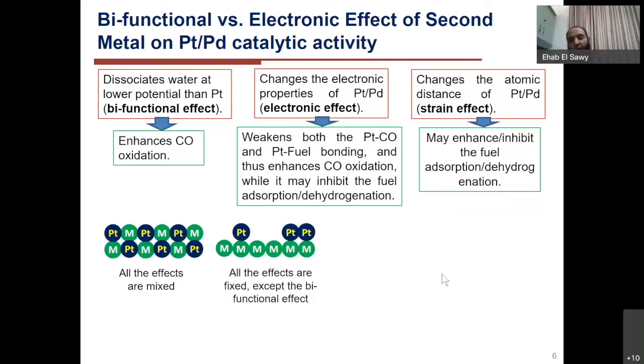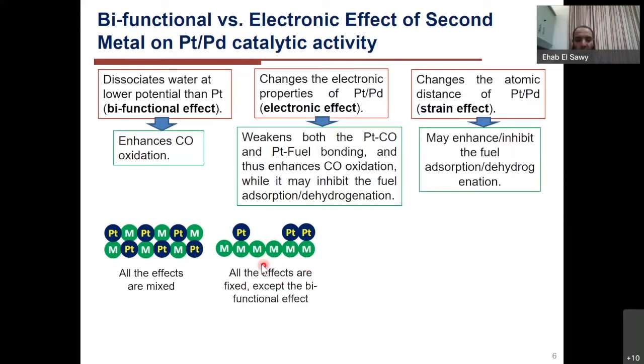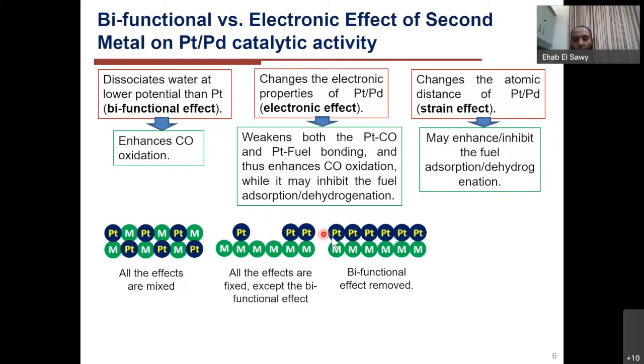So if we have the core in here and then we have a sub-monolayer of the shell on the top, in this case the electronic effect on these atoms and the strain effect are constant. However, if we are changing the shell coverage, we are only changing the bifunctional effect as the second metal is exposed. However, if we are totally covering the metal with one monolayer of the platinum, in this case we're removing the bifunctional effect and we only have electronic effect and strain effect.